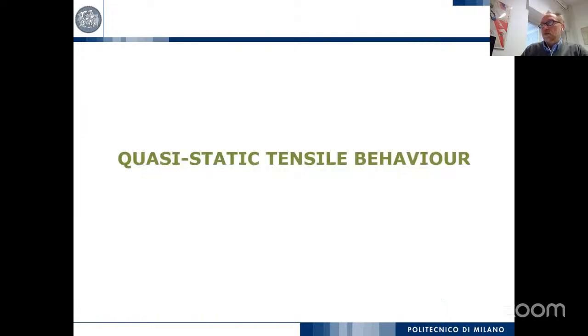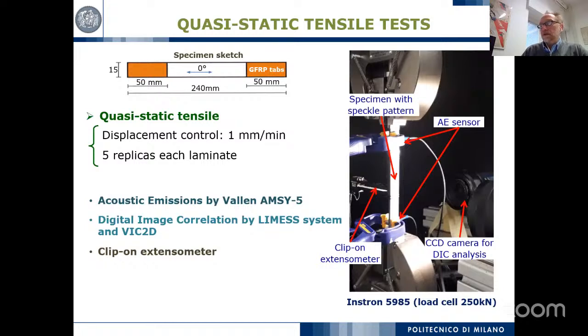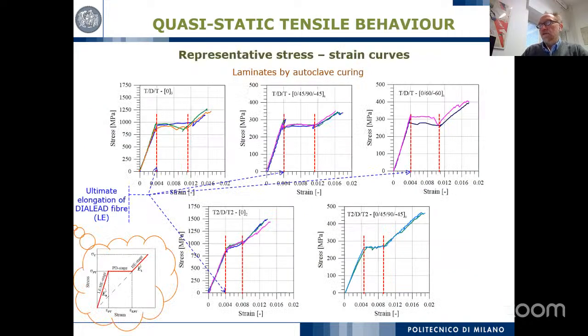Anyway, moving to the static test, this is a quite standard setup that includes acoustic emission recording, digital image correlation observation, and also a clip extensometer to have measurement of strain with both techniques. So we put all together. And then this is the final overview of the stress-strain behavior in tension, where you can see what we want to have. This is the schematic on the bottom left of what we would have for this material, including the pseudo-ductile stage. We have it in the results of the tensile test.